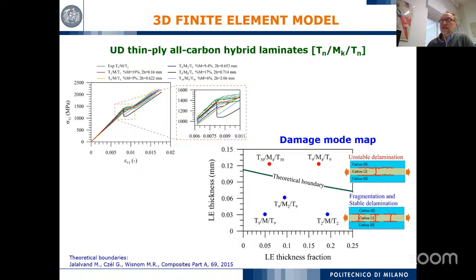to a larger number of laminates, and this has been done. The main scope of this is to create what we call the damage mode map that we have seen at the very beginning. Meaning we want to give advice on the different stacking sequences. If you change the stacking sequence, mainly in terms of the quantity of low elongation plies, we can distinguish the damage evolution: whether we have unstable delamination, where the delamination starts very quickly, or fragmentation, then stable delamination that creates this pseudo-ductility behavior. And these are the results of these several finite element models.